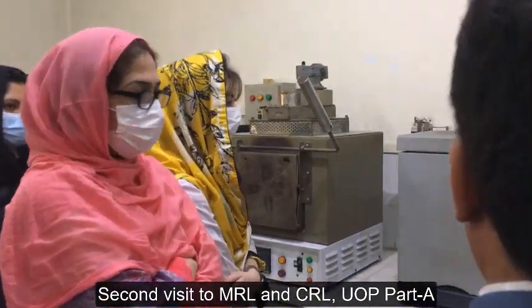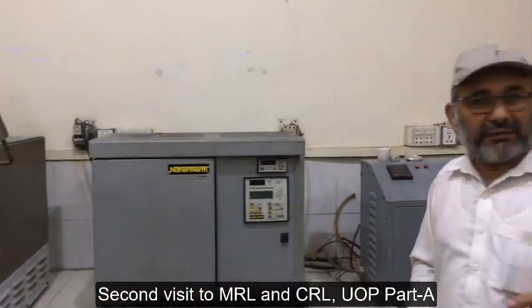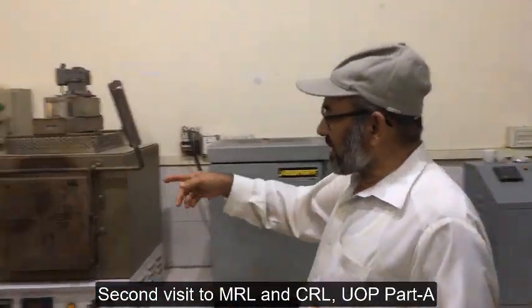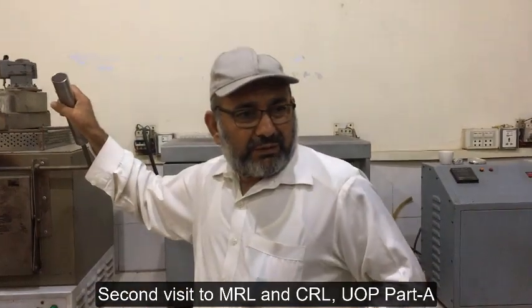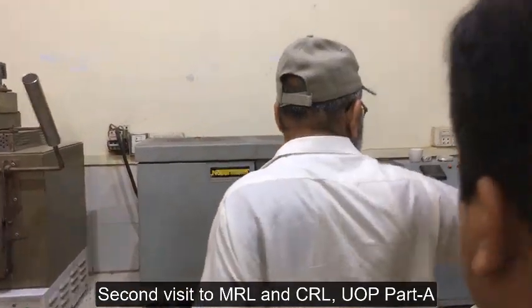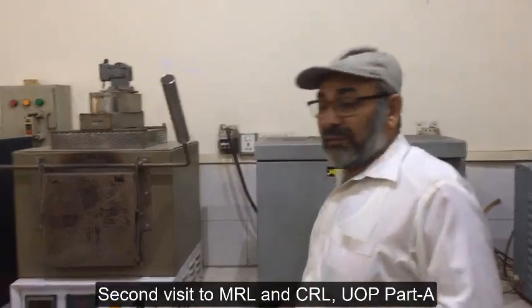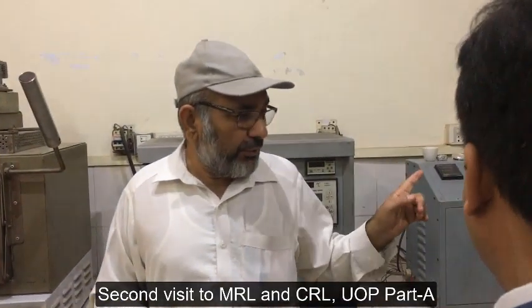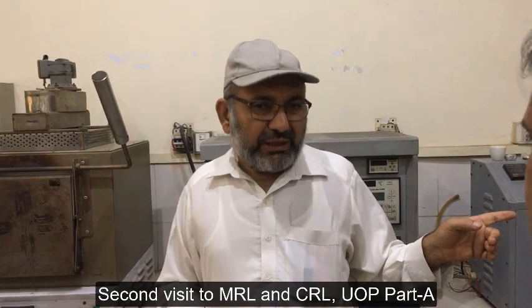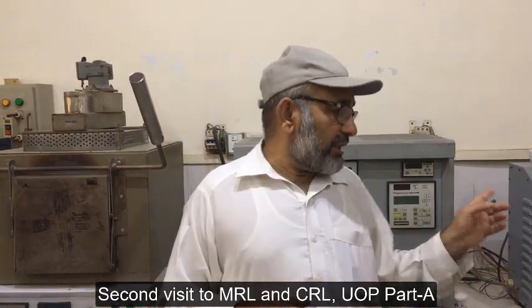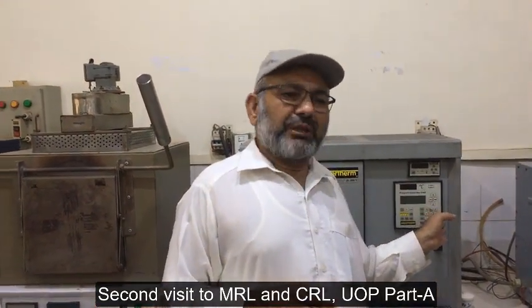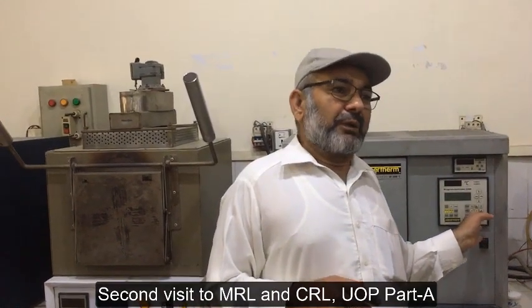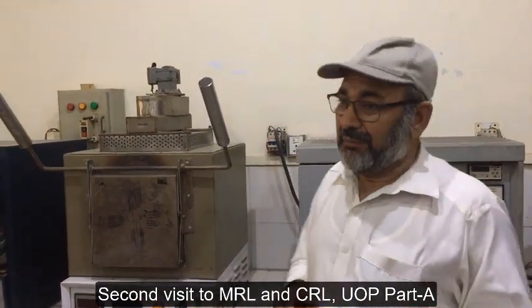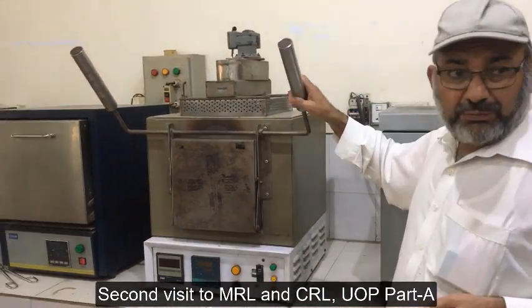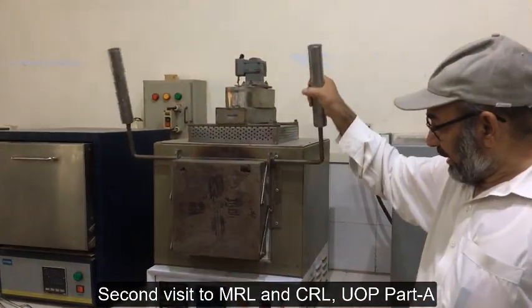This is a 1800 degrees Celsius furnace, mostly used for sintering of material at high temperature. Do you have the treatment for any nitrogen gas like this? We have that with that, not with these. Okay. Yeah, because there we have, and they are safe when they are opened at high temperatures. But these have probably molybdenum coils, so you can't open this furnace at high temperatures. They are damaging the element. This is a locally made furnace for glass melting, right?